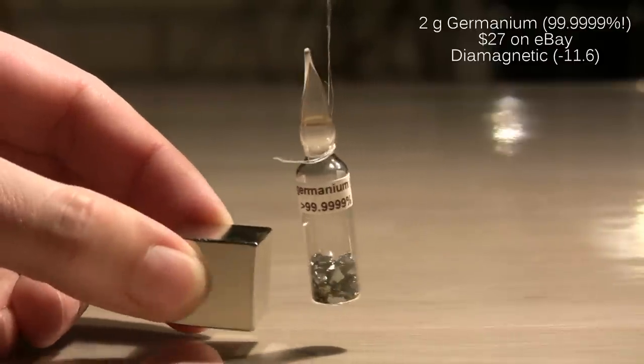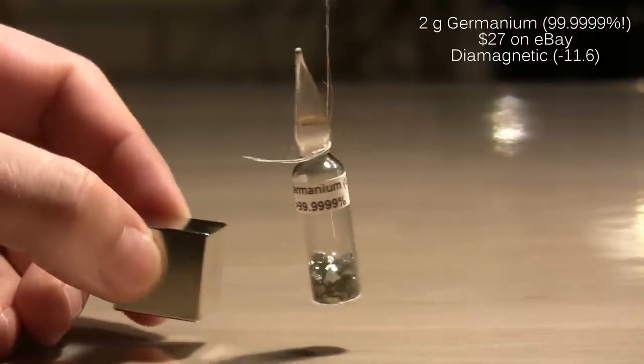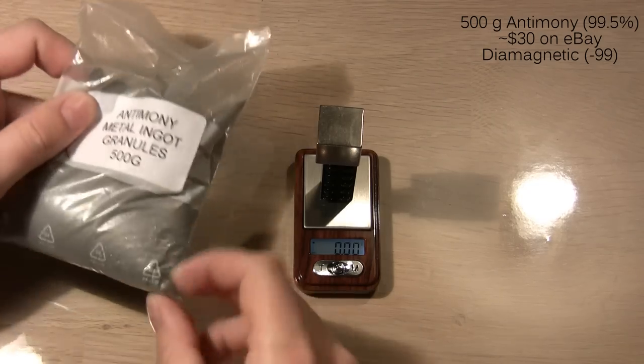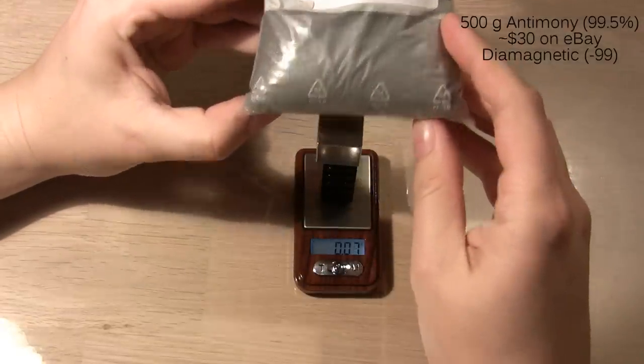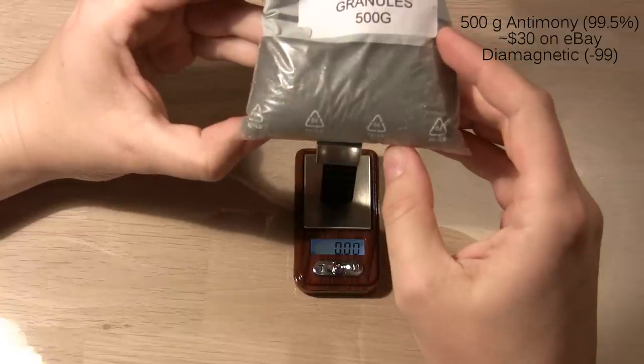I need to buy a better sample. Now let me show you one with a true reading. This is antimony, which is quite diamagnetic — about a third of bismuth. Without touching the magnet I get a reading of about plus 70 milligrams, which means that the magnet is repelled by the antimony with a force less than the weight of a match. Not much, but clearly there.